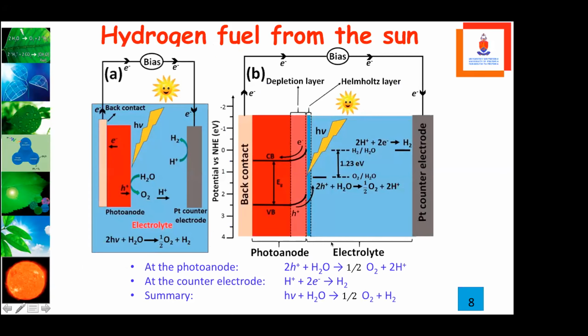All right, this is the process for photoelectrochemical water splitting. You shine the sun on your semiconductor, which is a photoanode, and then you create electron hole pairs where electrons are attracted by a bias to the platinum counter electrode. And then this blue here is the water. And we say at the photoanode, the oxygen is evolved, and then at the counter electrode, that's where we produce hydrogen. That's why we speak about water splitting.